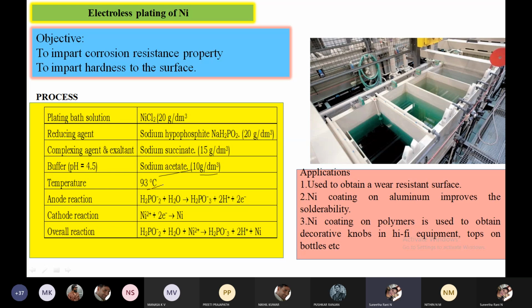The temperature we maintain is 93 degrees Celsius. So the additives are nickel chloride, sodium hypophosphite, sodium succinate, and sodium acetate. After adding all these into the vessel, we call it an electroless bath. The bath is just a vessel, a container where we add all these chemicals or reagents.